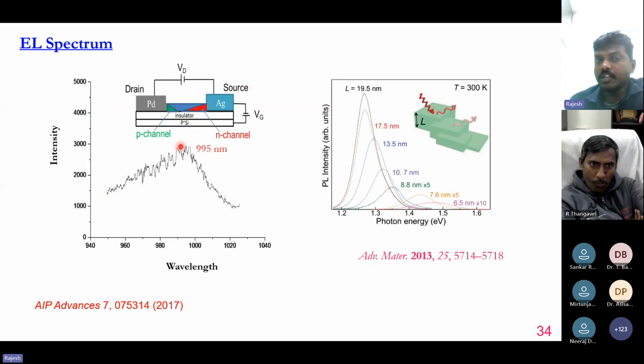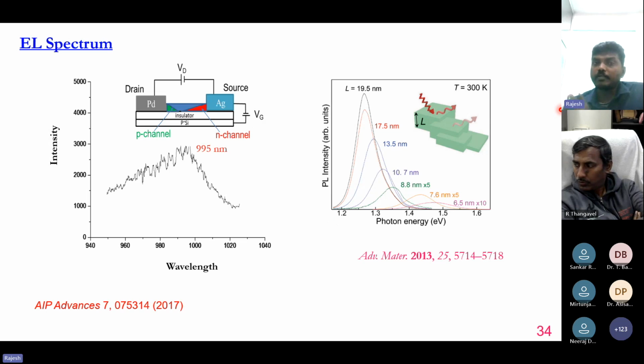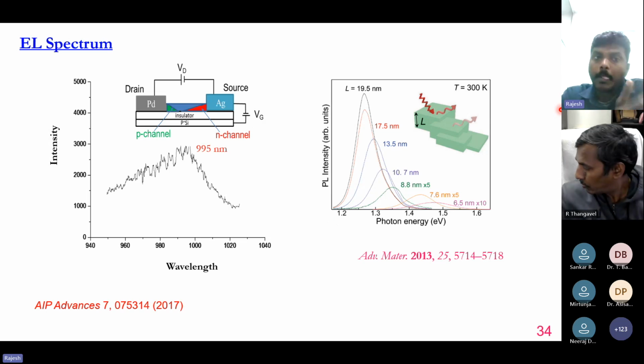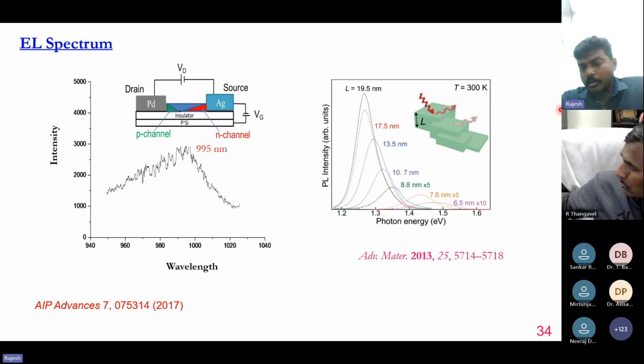This recombination creates electroluminescence, and we observe a wavelength around 1000 nanometer, which clearly conforms with the band gap of indium selenide, which is around 1000 nanometer. In this way, we are able to show that indium selenide can also act as a good LED application with the help of various combinations of electrodes.